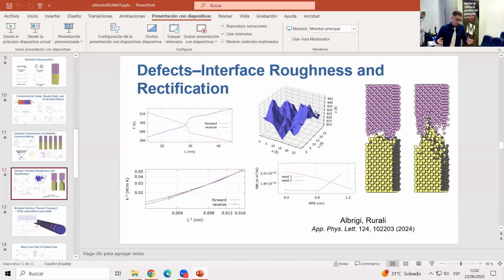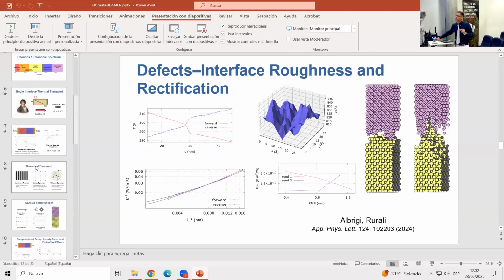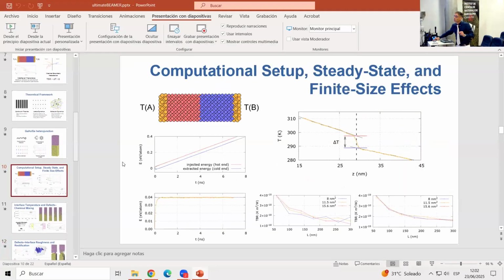And this is just a computational compromise that we need to accept, because in order to perform this simulation, we have to use a very fine resolution. Here I'm simulating 7 nanoseconds. To simulate 7 nanoseconds, I am solving the equations of motion for 100,000 ions with a resolution of 0.7 femtoseconds, so I am performing something like 10 million steps for 100,000 atoms. These are very heavy simulations. You need to run supercomputers for hours and hours and possibly days to get one single data point.